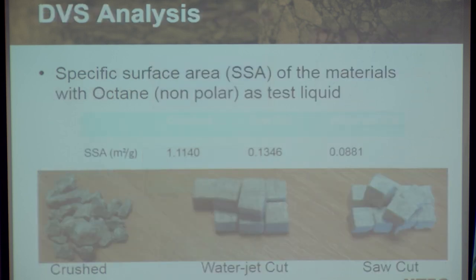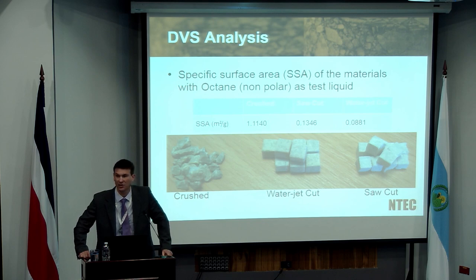We also were very interested in this surface area. Remember, I've mentioned at least two occasions so far, surface-specific area is an important component of adhesion. Obviously, the bigger the surface area you've got for your bitumen to bond with the stone, the better. And so, again, we were very concerned to make sure that when we produce these substrates, we weren't artificially changing the surface-specific area of our aggregates. And so what we ended up doing is producing a range of, some of them artificial, but some of them real aggregates that have been crushed in a plant and produced for asphalt. They're all nominally the same size, so they all were roughly about 1 millimeter square in terms of their cross-section.